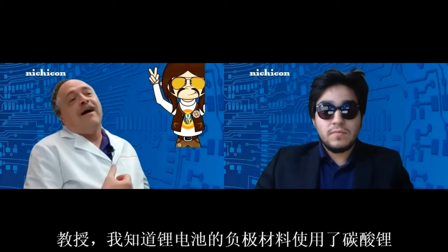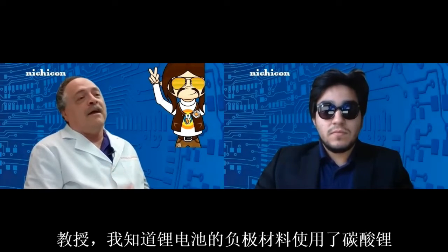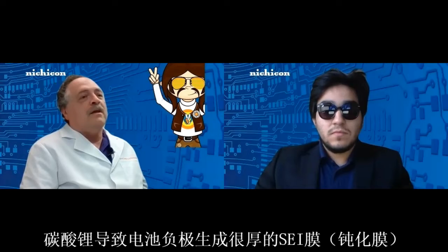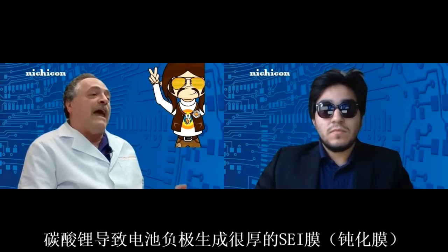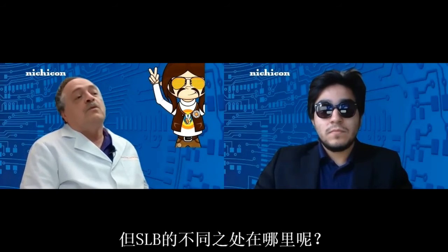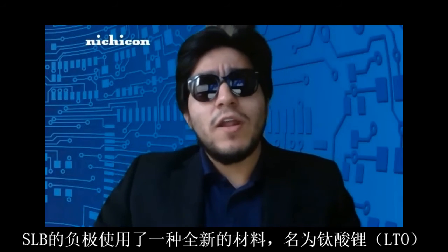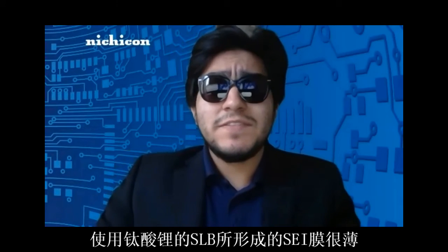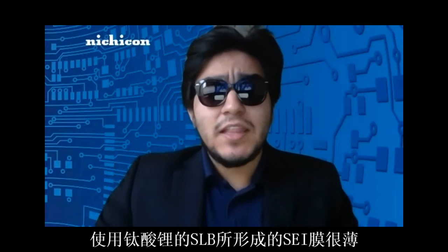Now, Professor, I know that standard lithium ion negative electrodes use lithium carbonate, which gives them the really thick SEI layer. So what makes this SLB so different? You make a great point, Doc. The SLB negative electrode uses a brand new lithium titanate or LTO technology. This gives the SLB a thin SEI layer as well as low electrolyte decomposition and low resistance.